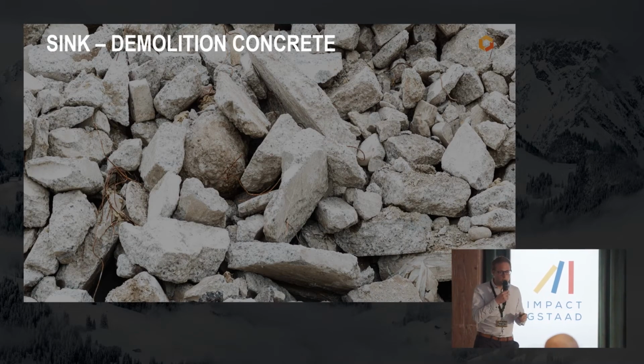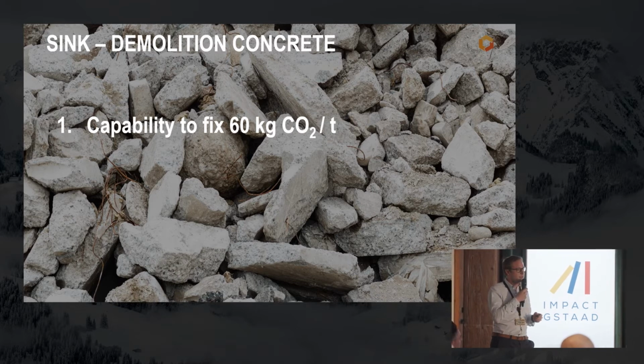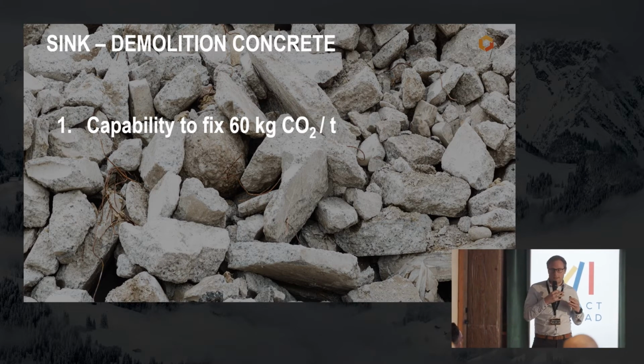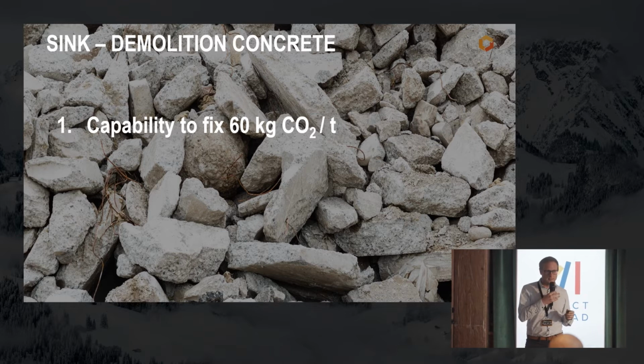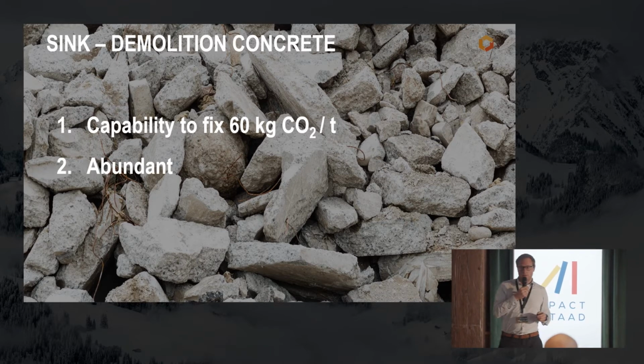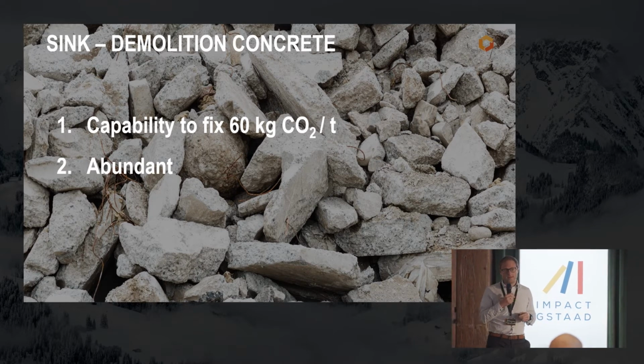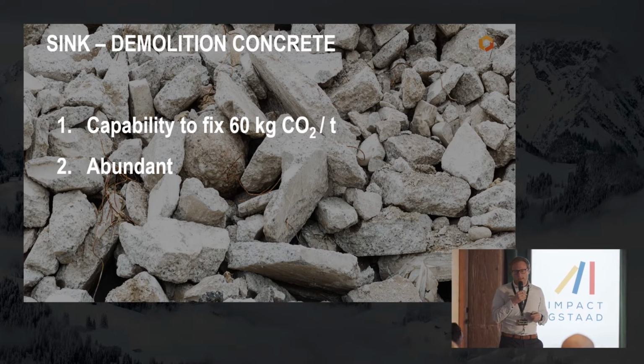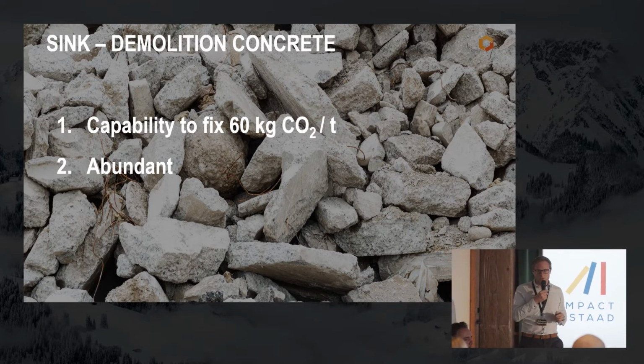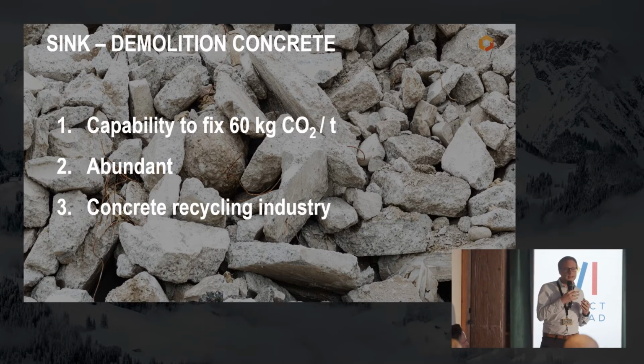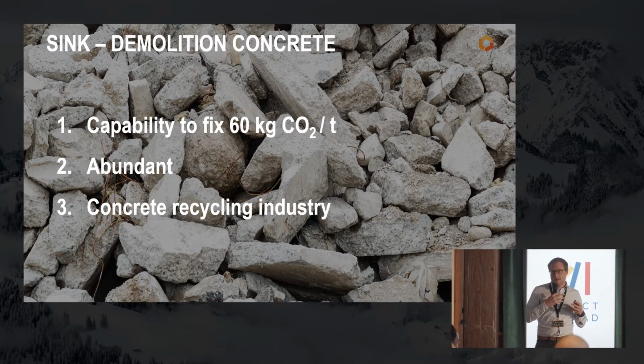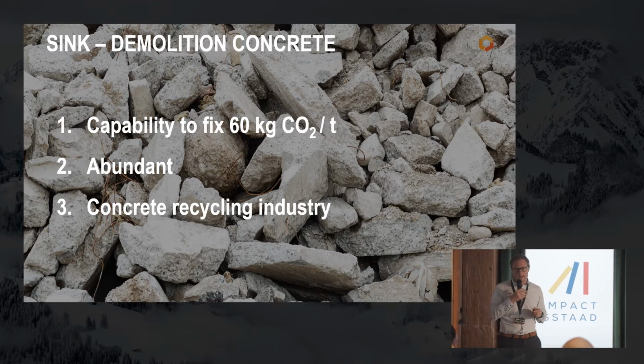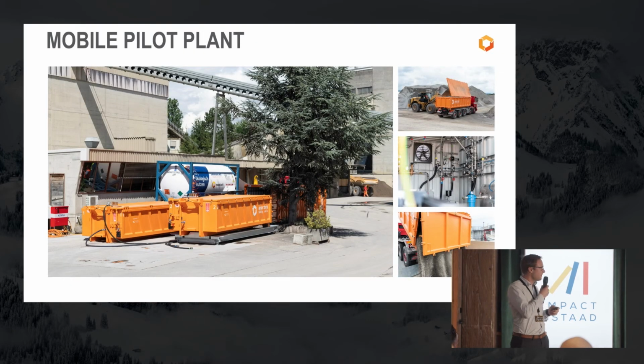So why do we use concrete? We use it because it has the capability to fix up to 60 kilograms of CO2 per ton of material. It's a very abundant waste stream. So in Switzerland, actually the most abundant waste stream, with about 5 to 10 million tons of demolition concrete per year. And there is a recycling industry in place which already pre-treats the material in such a way that it's ideal for carbon storage.